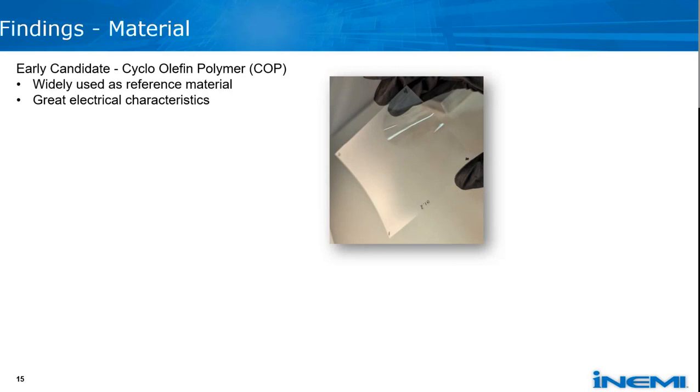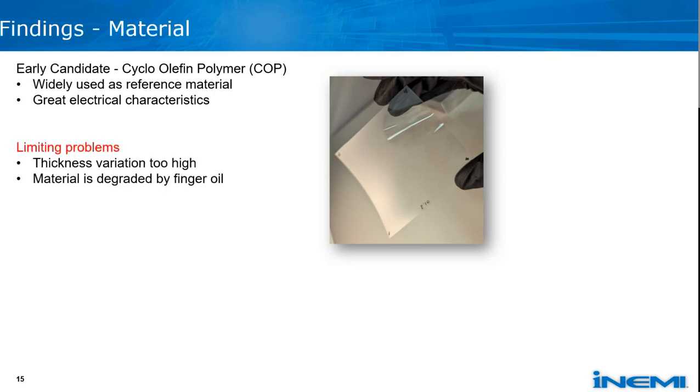If you look at what they are physically, they look generically like a piece of plastic sheet. They're flexible, clear generally. But ultimately we found that these materials, at least in the way that we could procure them, had more thickness variation than was tolerable for the SRM project. And when I say that, you have to think that the thickness variations we're talking about are like 1 micron. So even though these sheets are for all practical purposes and industry use cases really uniform and very highly smooth, 1 micron is enough to mess us up.